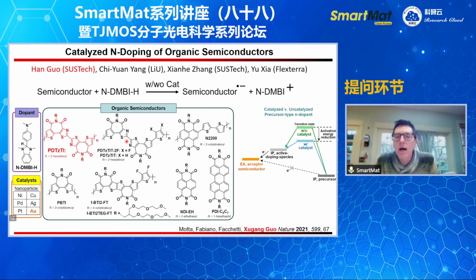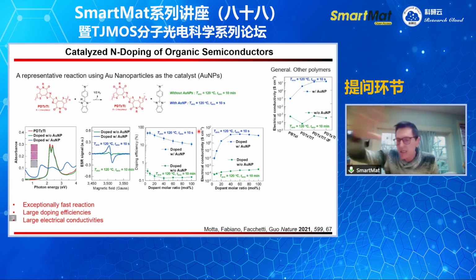For some polymers, for example N2200, we saw a typically quite dramatic decrease of the field effect mobility when you have a lot of dopants, and this is typical for this polymer. For others, with the doping, the field effect mobility increases, and then it remains roughly in the same range. So it really depends on the polymer. This is, at the very high level, my answer. Okay, thank you.